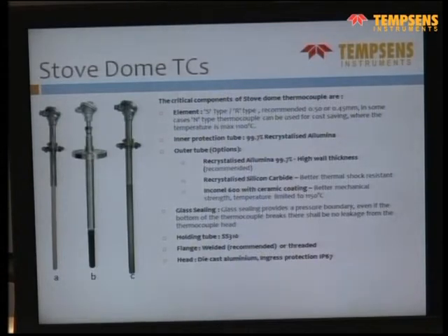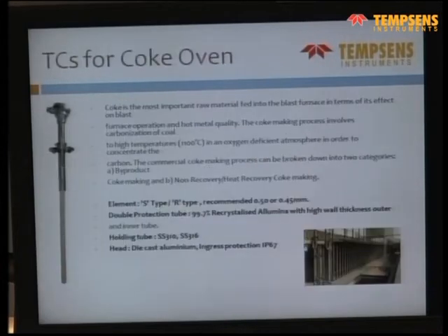And in this case also, just below the head at the top, we use a glass to metal seal. So even in case the thermocouple fails, the blast would not come out from the head. So this kind of solution we are offering, and it could be applicable for some of your cases also. We are using glass sealing so that even if the thermowell is breaking, the blast is not going to come out from the head. So this is for the stove dome.